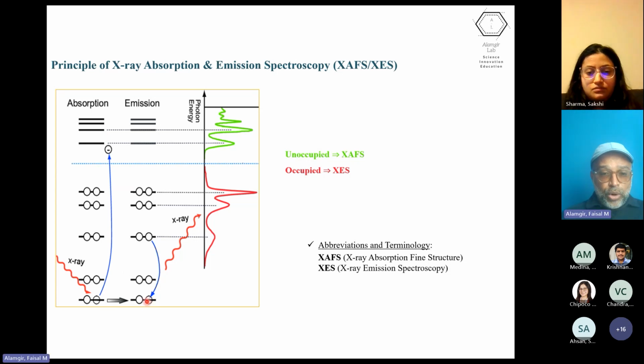Now, that core hole that's left behind by the absorption process is a very short-lived core hole, on the order of femtoseconds. So in that time period, another electron will try to come in and quench that core hole, because otherwise the atom is in a highly unstable excited state, and the quenching process goes some way to returning the atom back towards the ground state. So that electron coming down will come from another characteristic level within the atom, which means that the energy difference between where it comes from and where it ends up becomes a characteristic emission X-ray photon. So one electron dropping down releases one photon. So there's that one-to-one correspondence there. And that photon carries the information about the atom.